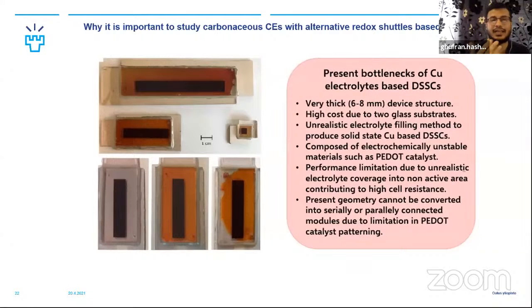Secondly, as I mentioned earlier, you produce this solid state cell by first injecting the electrolyte through the holes, and then you wait for the solvent to evaporate from the channel, and then you introduce it again and again. So it's a very slow process, and that cannot be opted for mass production or rapid production. So some alternative materials or methods should be developed for the introduction of this electrolyte in the cell channel.